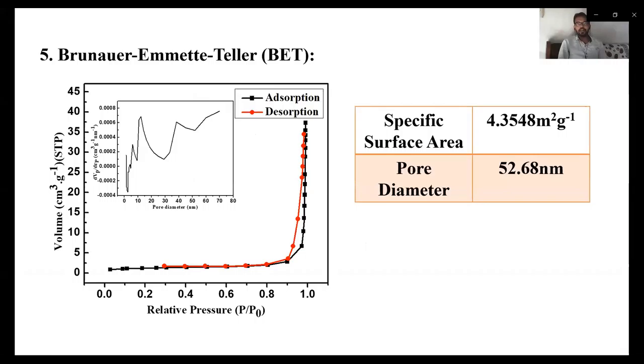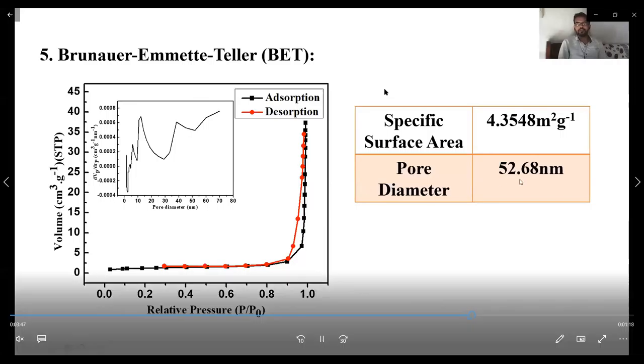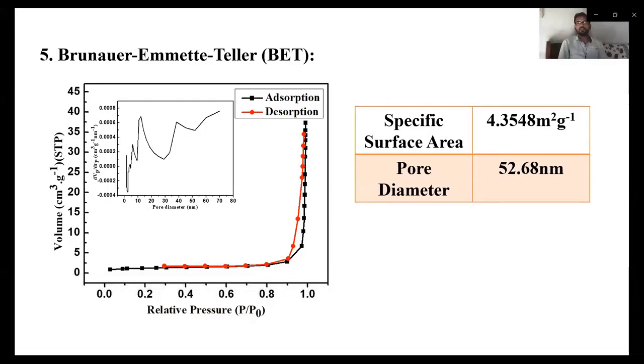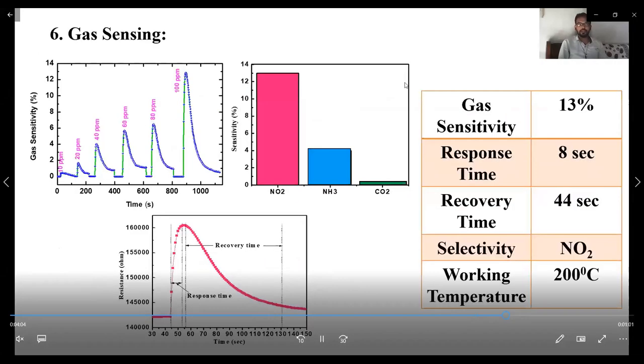This is the Brunauer-Emmett-Teller characterization, that is BET. The curve shows the N2 adsorption-desorption isotherm, and this curve is a BJH curve. These both curves are useful for calculation of specific surface area and pore diameter. The specific surface area is 4.3548 meters square per gram. Pore diameter is 52.68, which shows macropores. And macropores affect less the diffusion of NO2 gas, the NO2 adsorbed gas, which plays a vital role during gas sensing.